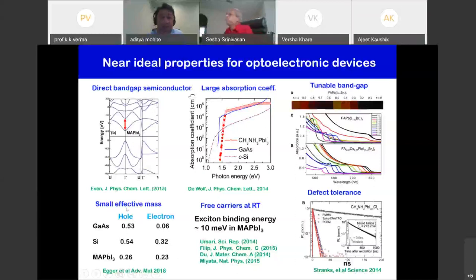Also, it has small effective masses. What does that mean? It means that if the mass of your electrons and holes is small, they can move about very easily. And so your mobility is typically high, and so you can transport them very well. And so typically, if you're making a device, you want this to be quite low.